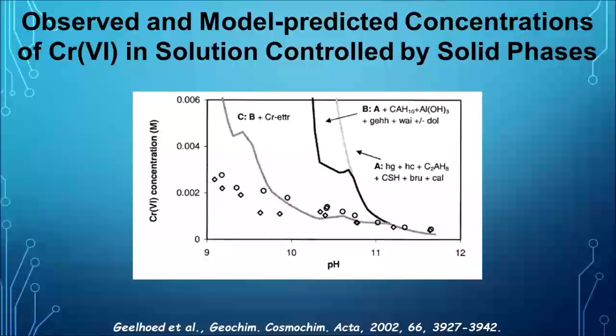That was the one with the beautiful needles. From the literature, what we found was that as hydrocalumite dissolves, then typically what happens is that chromium-rich ettringite tends to precipitate. So once we allowed precipitation to be part of the model, then we see a much better fit of the data down to now about pH 9.5-ish, thereabouts, before we have the discrepancy.